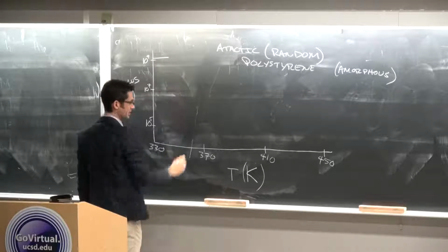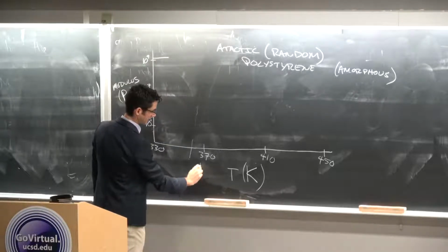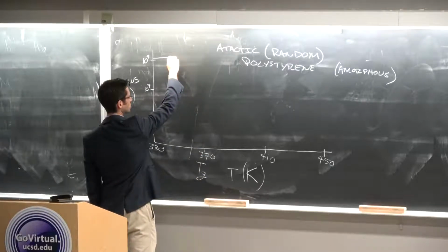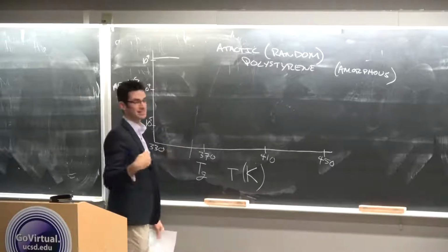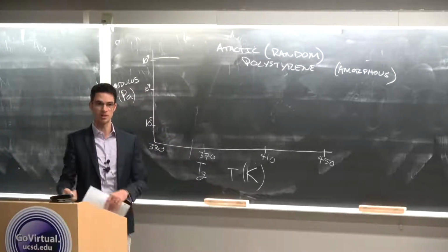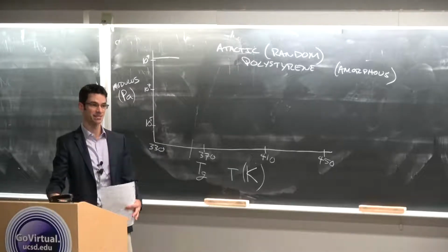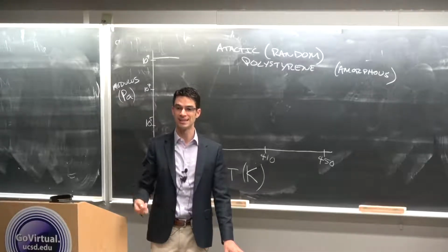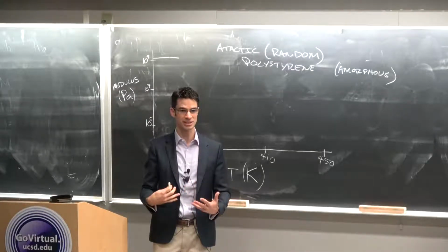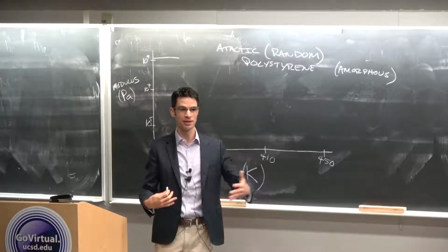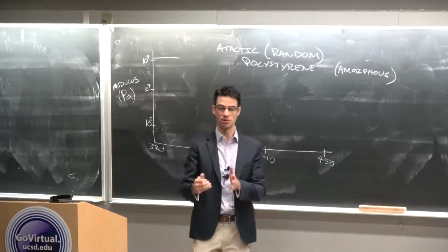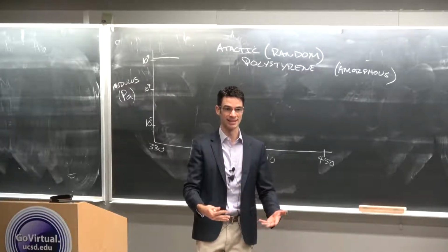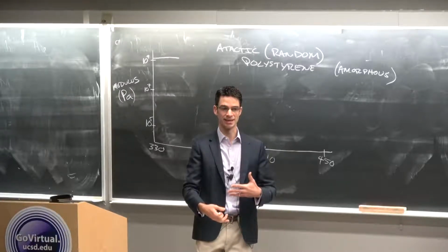And then the glass transition temperature happens to be 370. So as we go toward the Tg, it's not really an abrupt transition. Some of the polymer chains move at different activation energies than others. In fact, unlike a Tm or a Tc, there's no latent heat of a glass transition. So it's more of a smooth transition from below the Tg to above the Tg, whereas we know in crystallization and boiling and condensation, it requires a latent heat.